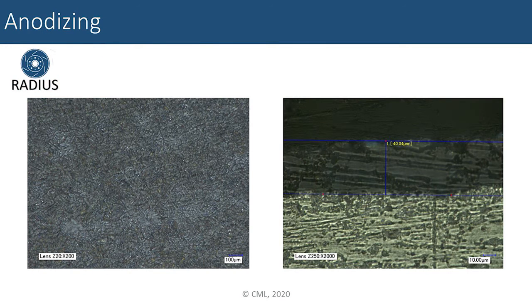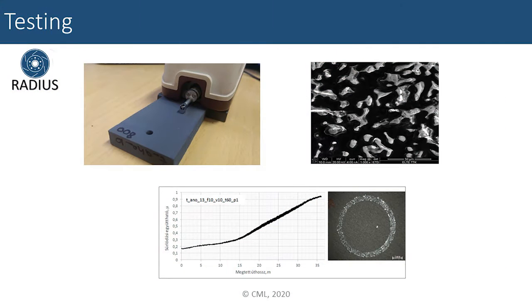The anodizing method is a low voltage electrolytic treatment in which we use a relatively less hazardous chemical as the electrolyte. The best results were delivered by the anodizing method, so we continued to further develop this coating technology. We tested several parameters regarding temperature, current density, and the concentration of the electrolyte. The results were evaluated by various measurements, such as the roughness of the samples, the phase composition of the coating, the hardness, and the wear resistance. Finally, we got the desired results for the test samples.